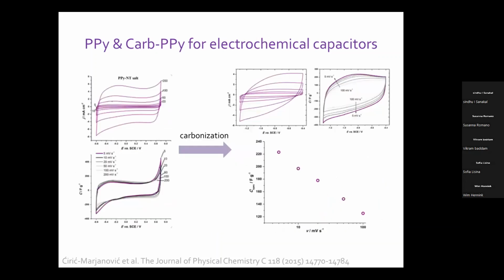So what we could actually see is that capacitance increases really nicely, and we got some values which are approximately 200 F per gram. It is still much lower than, for example, polyaniline that I showed previously, which had capacitance around 700 F per gram. But this is carbon material, and you can use it in different electrolytes, and you can expose it to very high anodic potentials, and it will preserve its properties. So there are significant advantages in terms of stability, but capacitance is a little bit lower.